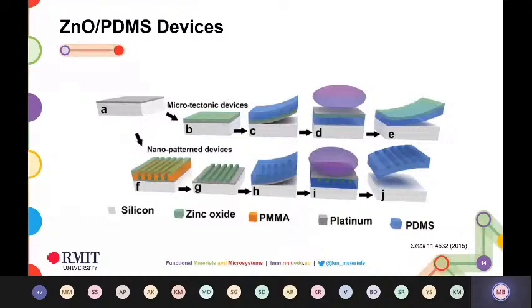It's a fascinating transfer process because we did the usual thing. We sent it off to review to a journal, and the journal asked us the usual question of whether it works for ITO or does it work for other materials. And we've tried quite a few different oxides along this journey now. So for instance, this image shows you the transfer process for zinc oxide. Exactly the same process using platinum as a transfer layer, except in this case, you're using zinc oxide. You can either transfer it as an entire thin film, as shown in this image E over here, or you can nano pattern it and then transfer it over, depending on your end application.